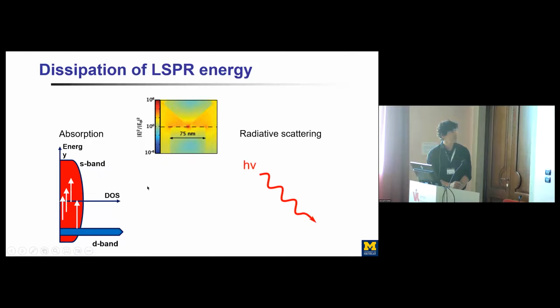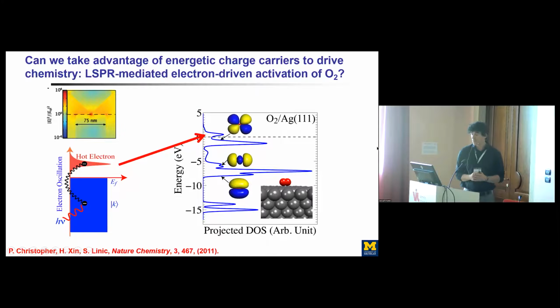The question that we had when we started in this field is really going back to that early study. So now if we are concentrating the energy of this electric field, or the energy of this light, at the surface of the nanoparticle, and if we can induce these electronic excitations at the surface under the influence of this electric field, is it possible then, under reaction conditions, for example under oxidation conditions, to use these electrons and scatter them through the anti-bonding orbital of oxygen, and in this process induce dissociation of oxygen with this light, as opposed to the thermal pressure, thermal heating that I discussed before?